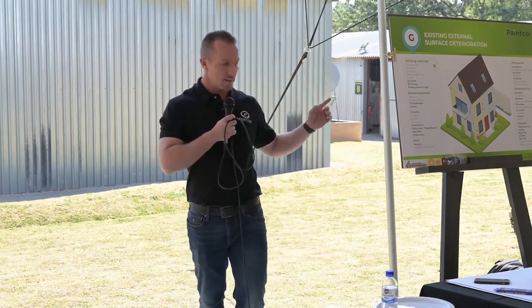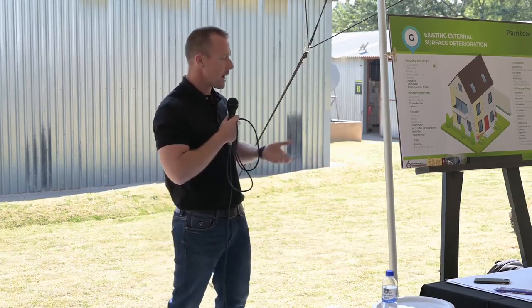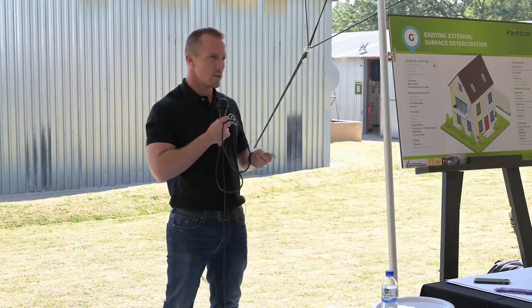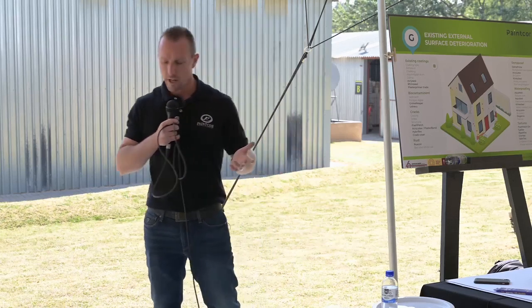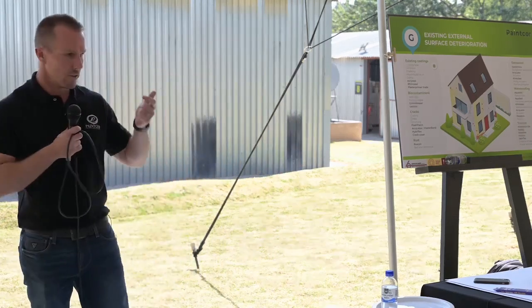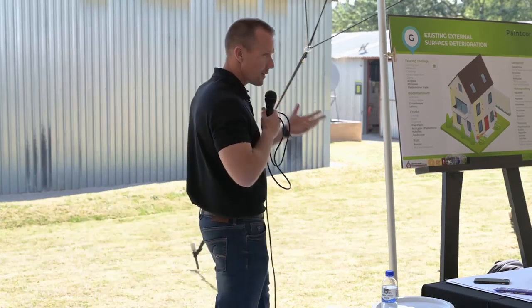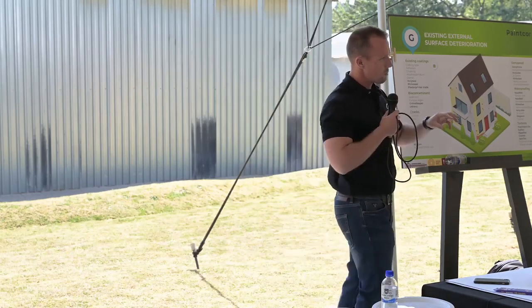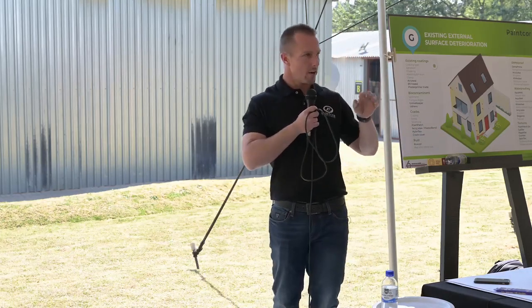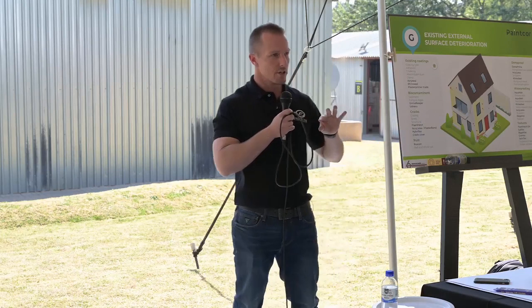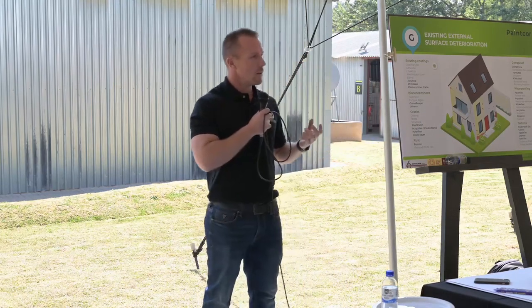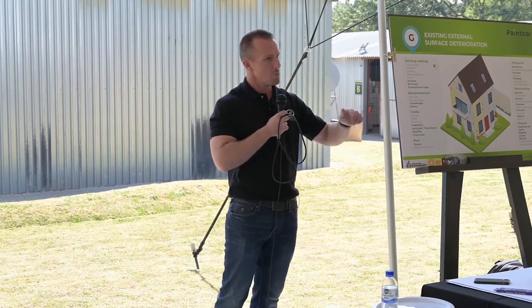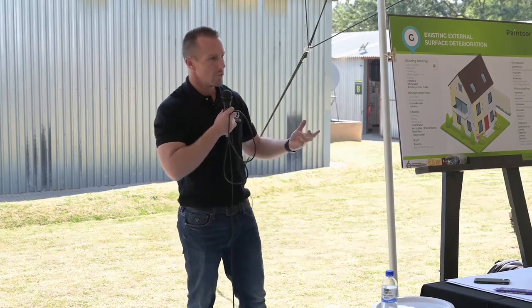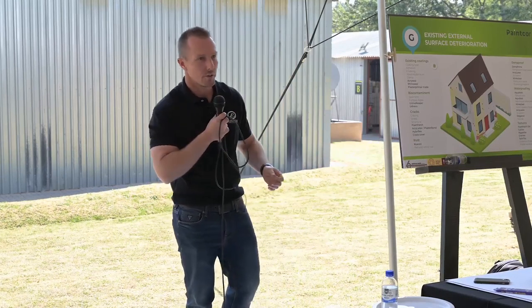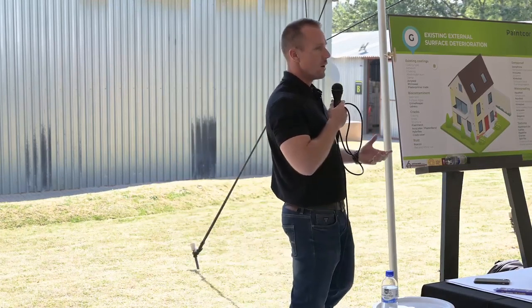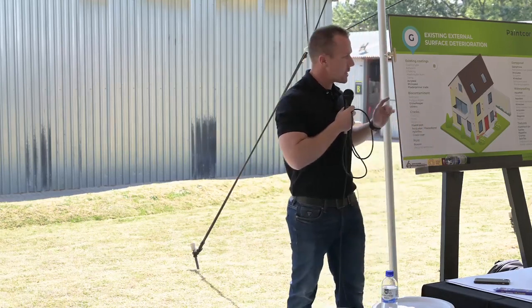It is in much the same way as the damp prime. It's a very high, low viscosity product, so very, very thin, thinner than water. It penetrates deep into the brick, not just brick, any masonry surface. So your Loffelsteins, your bricks, your molded cement, obviously plaster of all types. It goes deep into the pores because it's very thin. It finds all the capillaries, the little gaatjies and holes within your plaster structure, and it solidifies as actual silicone. So it stops water being able to transfer in, but what's beautiful is it allows moisture, in the form of vapor, to come out of that surface. So it promotes the continuous drying off of these areas treated for damp proofing without permitting any water going in.